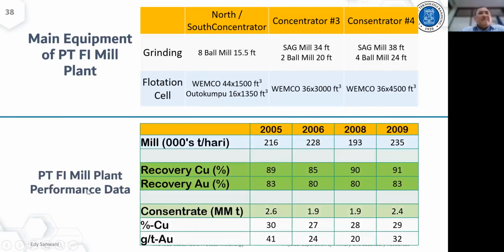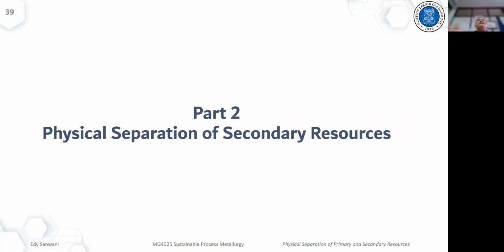This is the table of plant performance data, for example from the year 2005 until 2009. This is the capacity of the mill, the recovery of copper, the recovery of gold, and also the amount of concentrate in million metric tons per year, and then the grade of copper. Look here, the copper grade starts from less than 1% in the ore and becomes concentrate with a grade of 30, 27, 28, 29, even though currently it is around 25, even lower than 25, because more complex ore is treated in the plant. Okay, that's all in general for part 2, which is physical separation of primary resources.